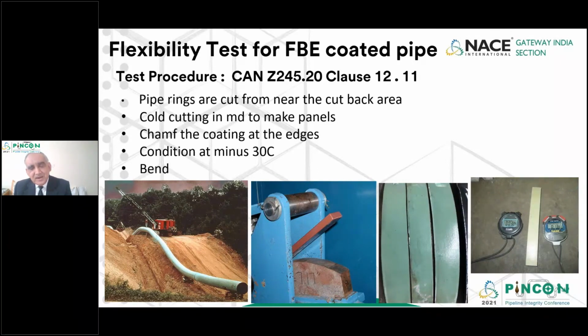After the panel is bent, it is kept on a table or platform with the stopwatch, and for at least the next 1 hour, 60 minutes, it is observed that it should not develop any crack or pinholes. And then a small low voltage tester is run over the bend to check if there is a discontinuity or holiday. So that completes the flexibility test method.